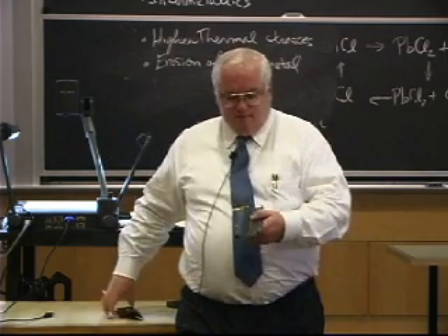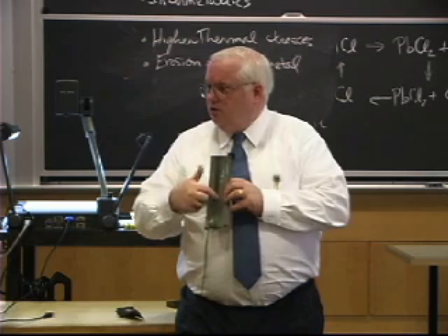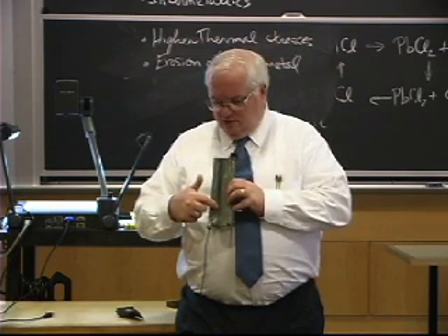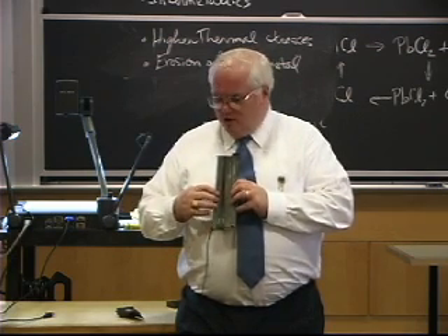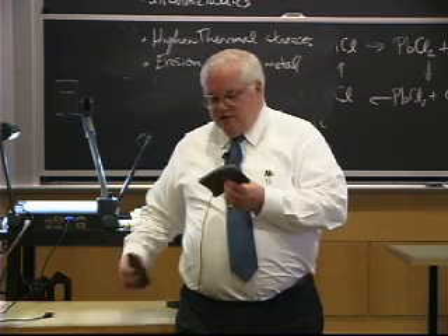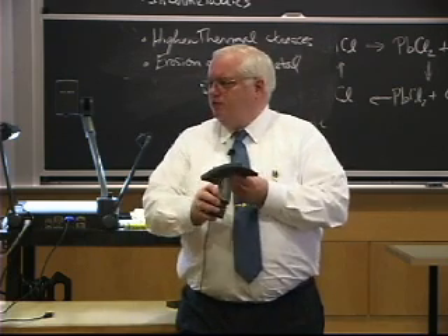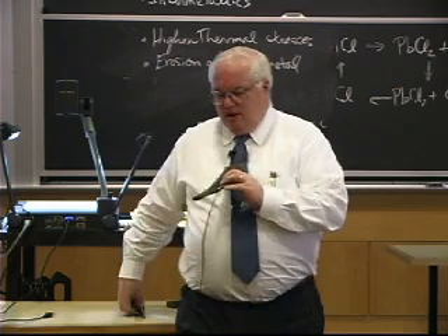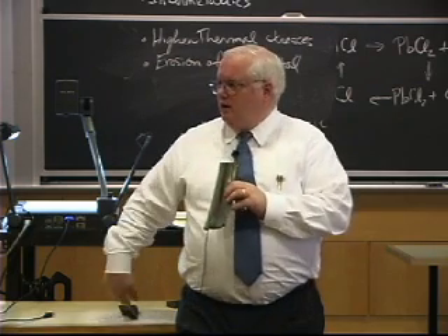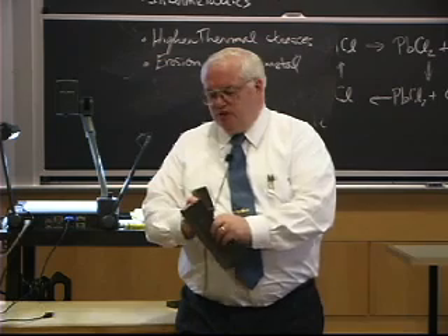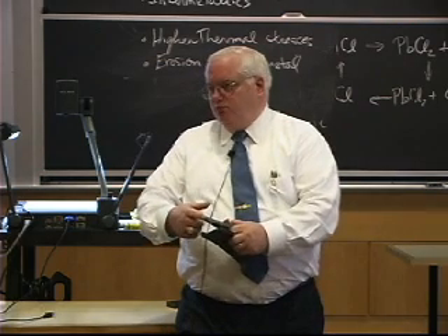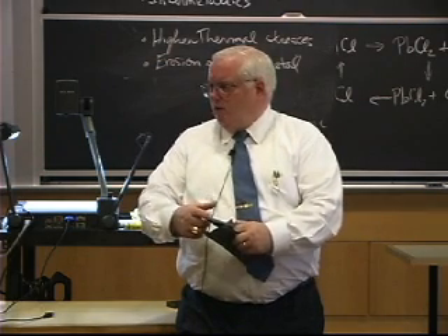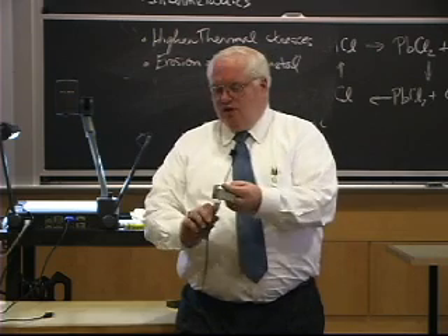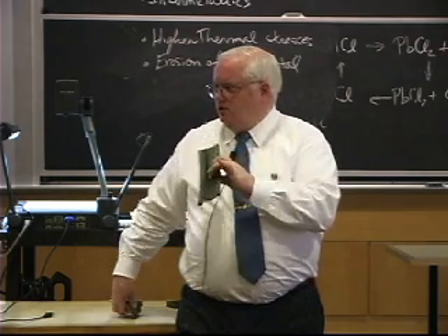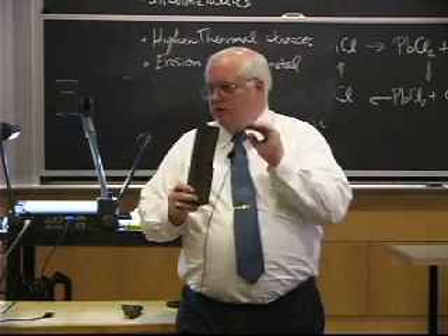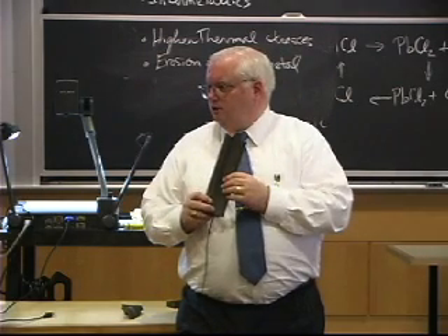So what do you do? You essentially make a honeycomb of metal and braze it to the substrate. And now this thing has something that will form a seal. It will rub up against it, and it will basically just eat the honeycomb away without hurting the blade. In fact, sometimes the blades, this one doesn't have it, actually this one's been cut off, a lot of times the blades will have carbides brazed on the top so that it can eat its way into the shroud, okay? But it's often a honeycomb, and you're just doing that to prevent the backflow of gas in your compressor.